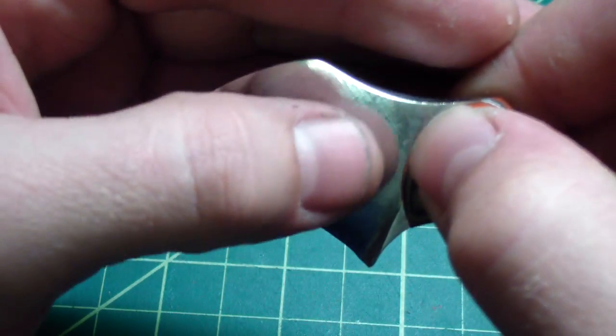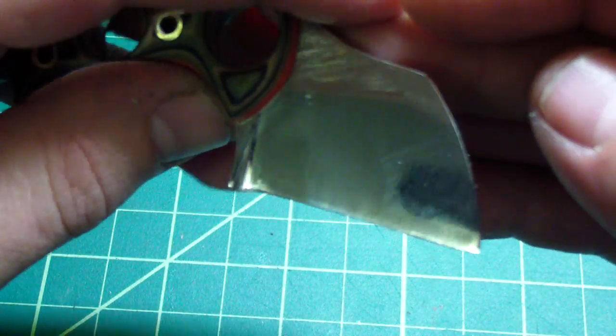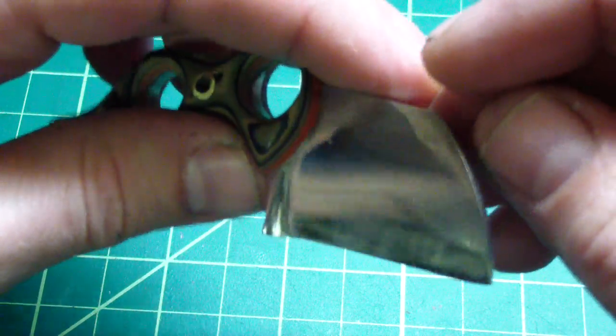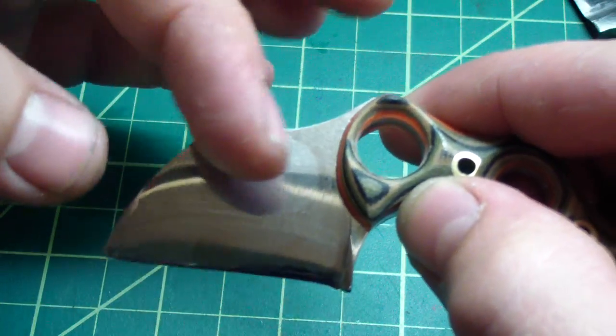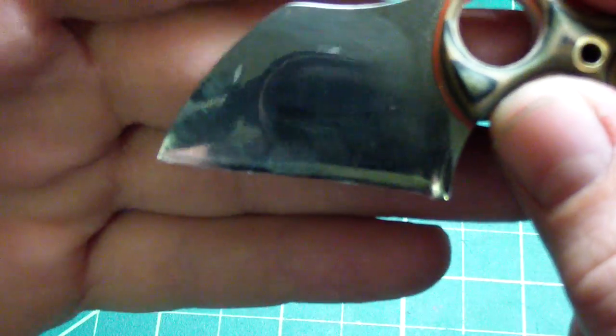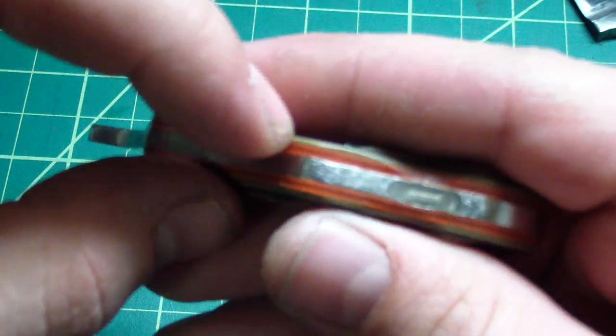It has those little grind marks in the polish, and you can see them. They're really hard to avoid on such a small blade because there's a big risk of overheating. On a big blade you go back and forth so it has time to cool down, but this blade is just a tiny bit bigger than the belt itself, so pretty much the whole time it's heating and heating. I'd rather have those little grind marks than overheat it.